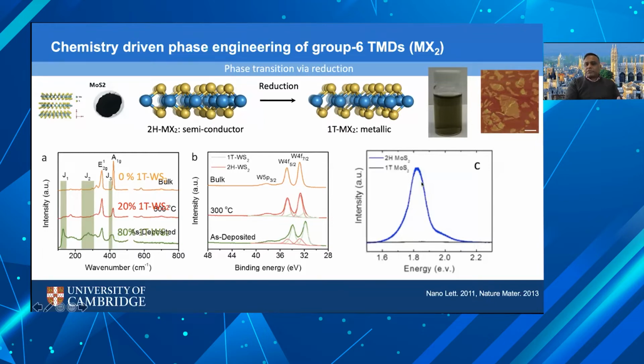degrees by measuring photoluminescence. So we know that for monolayer 2H MoS2, we have a nice PL because it goes from an indirect bandgap semiconductor to a direct bandgap semiconductor when you go down to the monolayer limit, with the A exciton and B exciton peak. And when we do the phase conversion to the 1T phase, we can see that the PL is completely quenched because it's no longer a semiconductor.